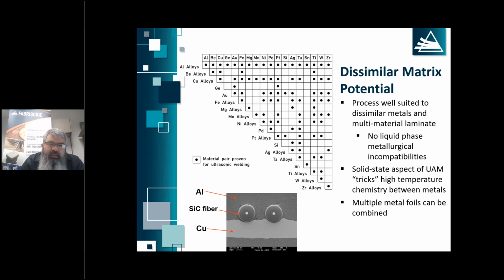The image at the bottom left, I want to make a little distinction here. We're seeing some silicon carbide fibers. Again, we've embedded pretty much every type of fiber you can imagine, embedded between aluminum and copper. And in this image, I would say the aluminum is metallurgically bonded to the underlying copper, but I would say that silicon carbide is embedded in the aluminum. So the welding process works very well to weld metals to metals, but it does not weld metals to non-metals.